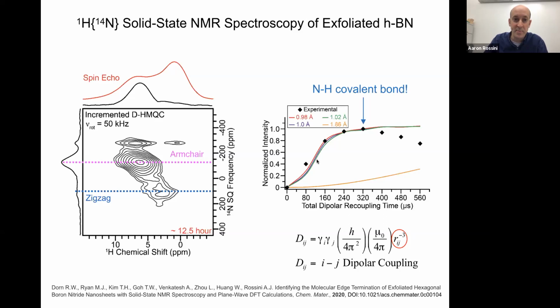In the HMQC experiment, we can easily vary the proton recoupling time and record a series of 1D HMQC spectra, and just monitor the signal intensity. We can then simulate that in SIMPSON, and we can fit that to get a dipolar coupling constant out. And we see that the dipolar coupling constant that explains this NH HMQC buildup curve corresponds to an NH distance of about 1 angstrom.